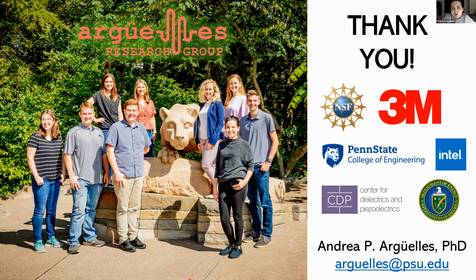thickness from the equation. So you have a calibration process for the time of flight. You're doing 2 time of flights, one for the known distance and one for the unknown thickness. Yes, sort of. It is a consecutive process of 2 measurements, but we don't need to know any of the distances, is what I want to make sure is clear. We don't need to precisely measure the distance.